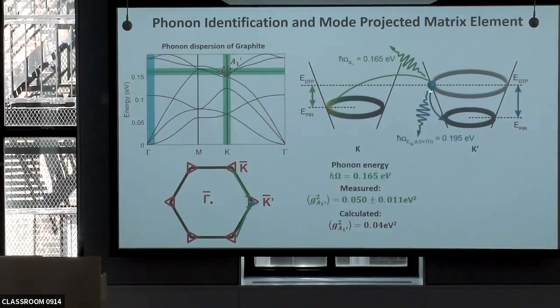If we look at the process, we can calculate for this particular state in K, so an electron here, you're scattering through a K mode, losing this amount of energy, and then you can calculate how the electron-phonon coupling goes for a small variation of that Q vector of the mode all around there. The calculation is usually done for one particle in this state, going down with that particular mode. And of course, it applies to the whole ring around the dispersion. So in this case, you have a measured quantity of 0.05, and the calculated turns out to be very close, 0.04. So in a way, the method works extremely well.